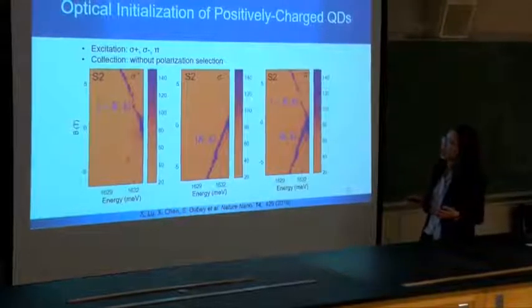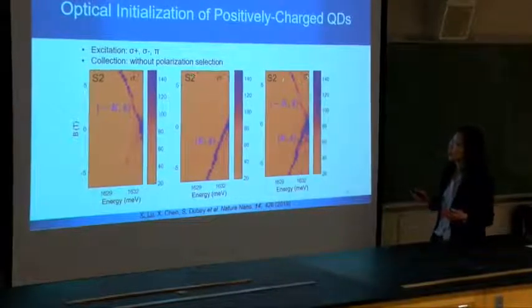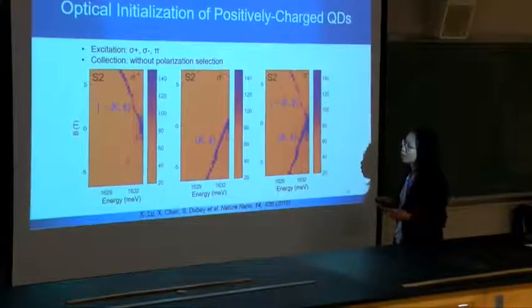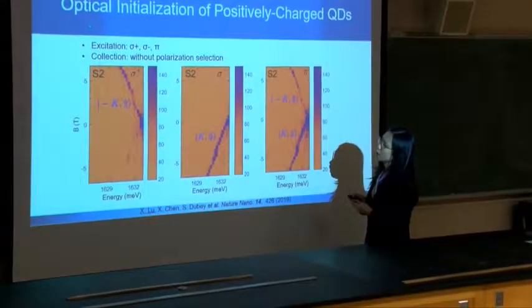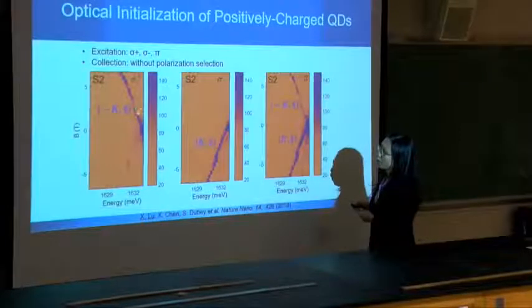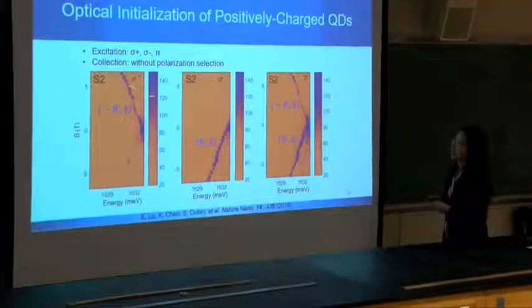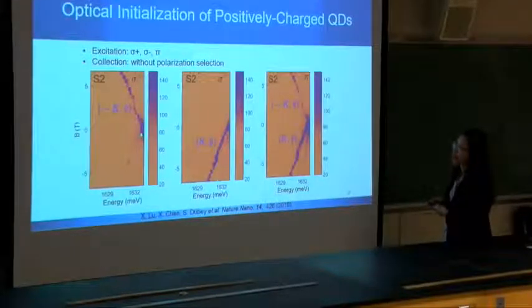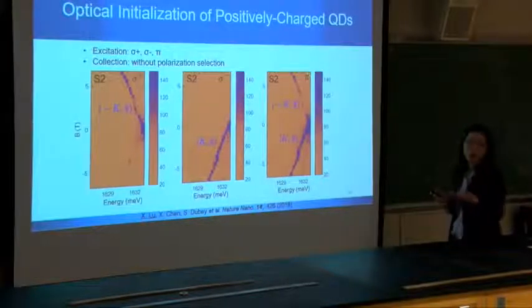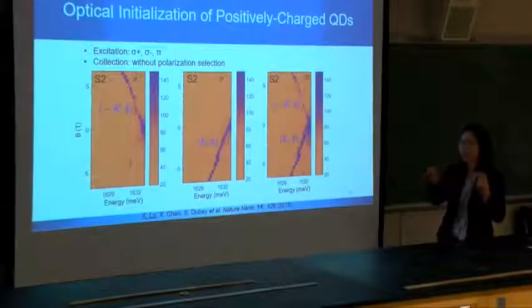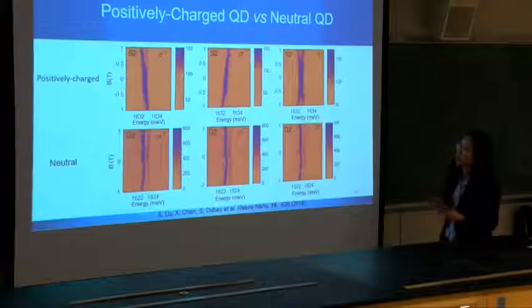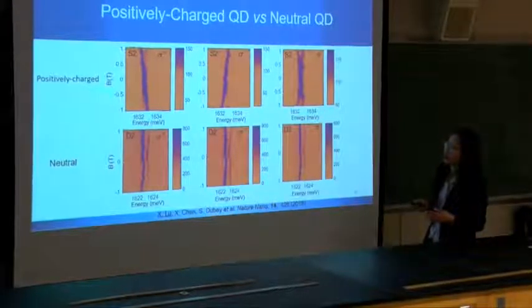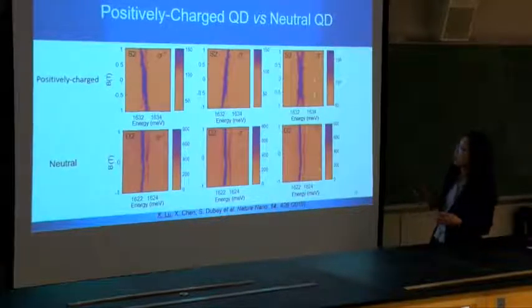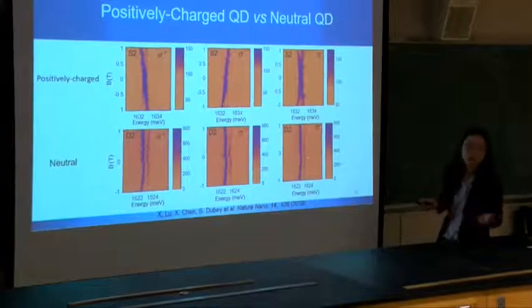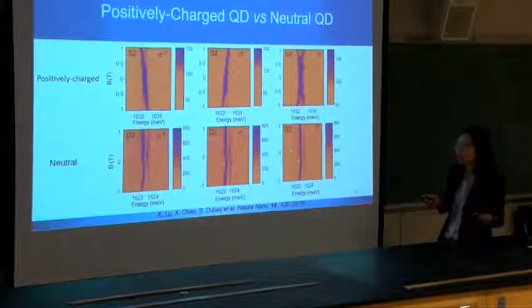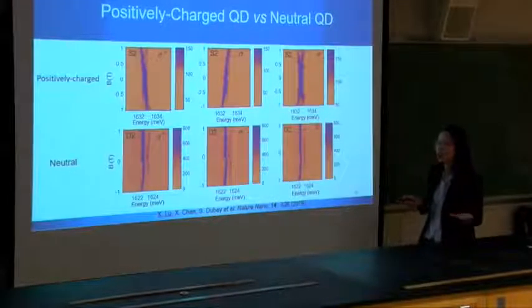So we change the polarization to circular basis. This is sigma plus, sigma minus, or linear. Here we cut the high energy part, just focus on one side. We find that with circular incident light, we can only see one branch. That's actually implying that we can successfully or efficiently initialize a single hole with a certain spin. And if we pump linearly polarized light, that's considered a superposition of sigma plus and sigma minus, we will see two branches. And here is a comparison between charged and neutral dot under sigma plus, sigma minus, and linear excitation. For the neutral dot, we would not see much difference between different excitations because there's exchange interaction. We can't actually control or initialize it.